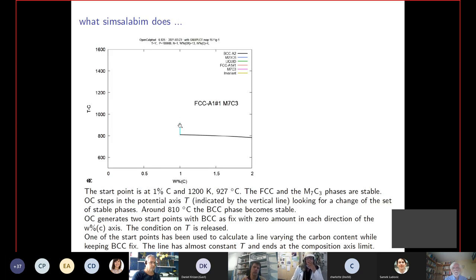So we have started with this point here. Then when you give the map command, it will look in some direction until it finds a new phase becoming stable. And here it finds the BCC becoming stable. And then it generates a start point from this node point. And it has two directions, one to higher carbon content and one to lower carbon content. And this has now followed the higher carbon content until it finds the limit of the axis we have defined.